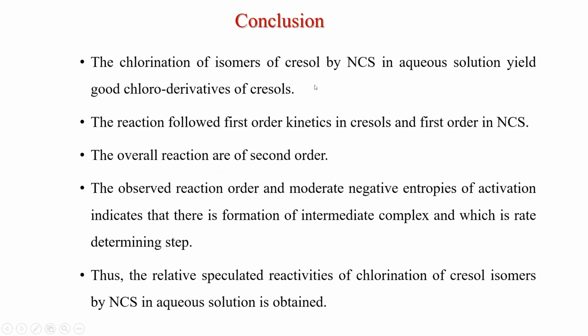This is the conclusion. The chlorination of isomers of cresol with NCS in aqueous solution yields good chloroderivatives of cresol. It is first order kinetics in cresol and first order kinetics in NCS. The overall kinetics is second order. The observed reaction has moderate negative entropies of activation, indicating the formation of an intermediate complex which is the rate determining step. Thus, the relative reactivity of chlorination of cresol isomers by NCS in aqueous solution is obtained in these studies.